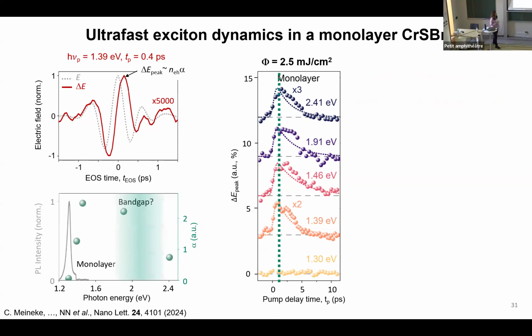What is the other interesting information that we can gain is to track the maximum of the pump-induced response as a function of the photon energy. Because this gives information about the polarizability and potentially the band gap. Let's see together. Here is this maximum as a function of photon energy. And for clarity, I just compared the spectrum of photoluminescence of the monolayer with our data. What we see is that by pumping with 1.3 electron volts, which is very close to the exciton 1s resonance, we have a quenched polarizability because we have such bound electron and hole pairs.